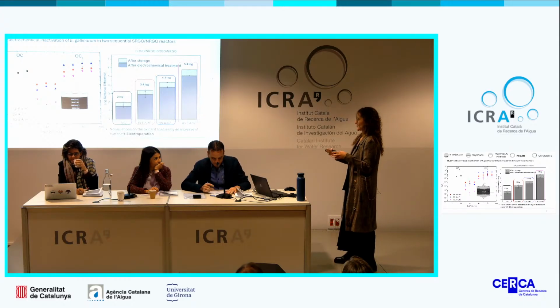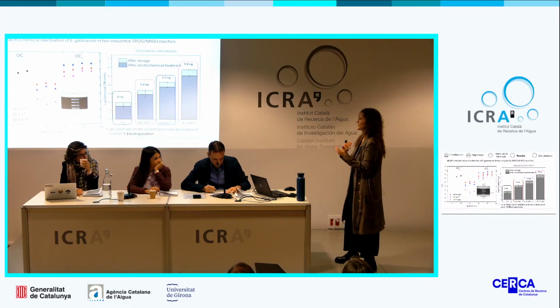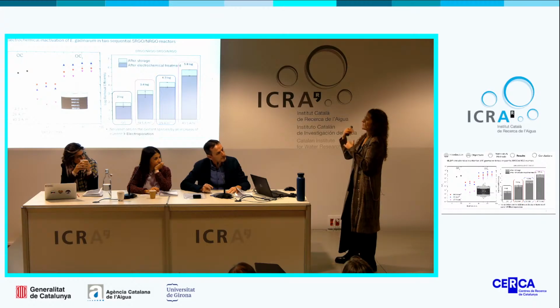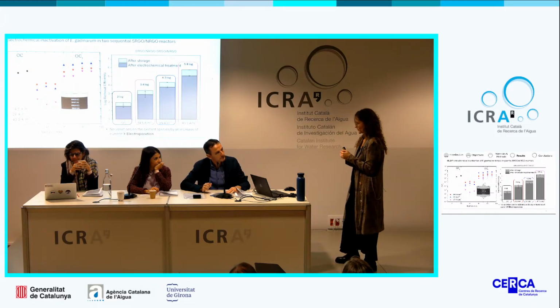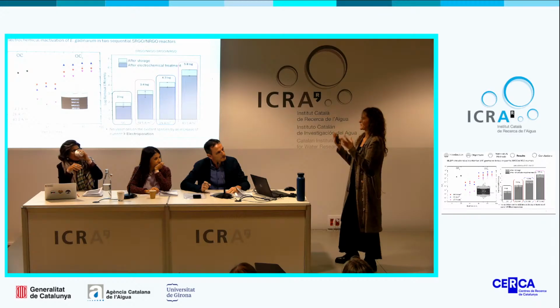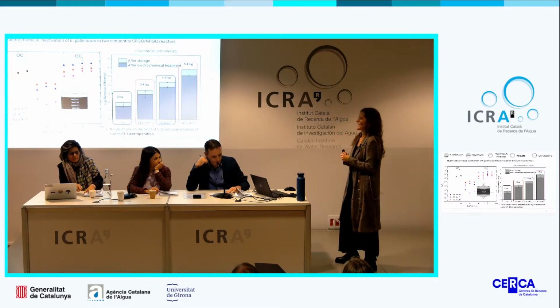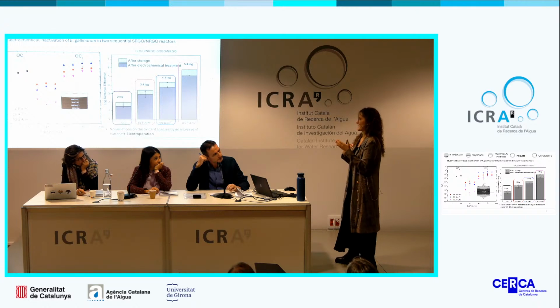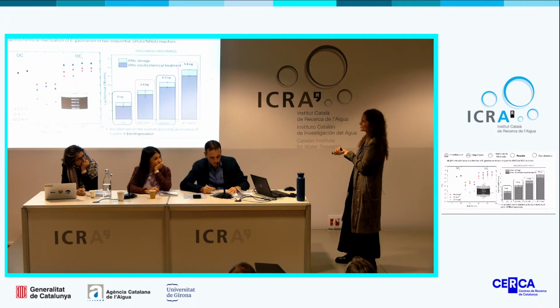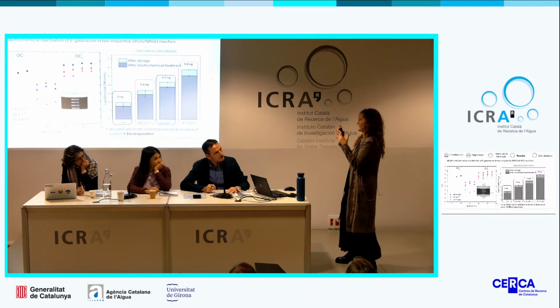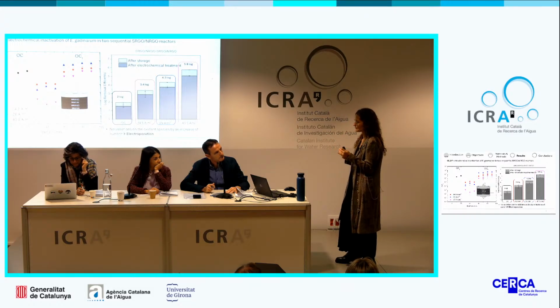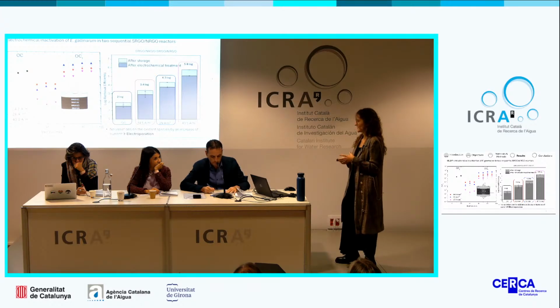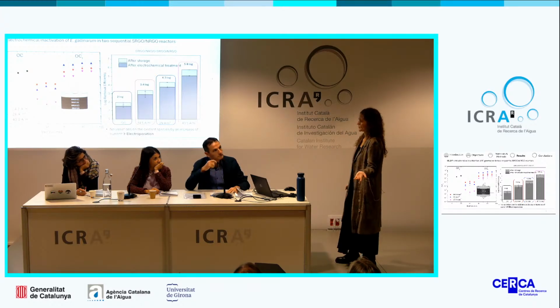No, in that case, it was to increase the wettability and the interaction between the contaminants and the electrode. Since we are enhancing the hydrophilicity of the material, contaminants, and when I say contaminants, I mean antibiotics and also pathogens, there is a better contact with the surface of the anode. For example, during the open circuit conditions, as we could observe, we are also able to eliminate part of these pathogens through direct contact with the electrode. So it's also increasing the inactivation of bacteria as well as the absorption of contaminants.